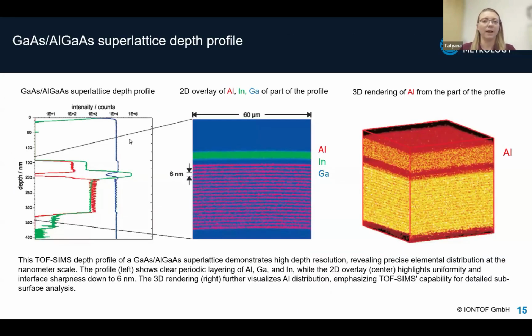Let's continue exploring depth profiling, this time focusing on depth resolution using an aluminum gallium arsenide superlattice. On the left, the depth profile shows clear repeating layers of aluminum, gallium, and indium. The 2D overlay confirms the same pattern, highlighting the precise separation of elements. What makes this result so impressive is the high depth resolution. We can map elements at the nanoscale with incredible accuracy. Notice how alternating layers stay well defined across the entire depth of the analysis. On the right, the 3D rendering focused on aluminum distribution adds another layer of information. This shows how ToF-SIMS provides detailed subsurface chemical analysis while keeping excellent depth resolution. Such precision is crucial for semiconductor manufacturing, where measuring accuracy makes a big difference in quality control.